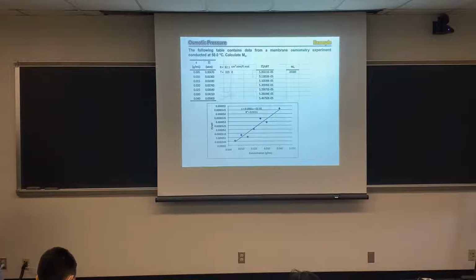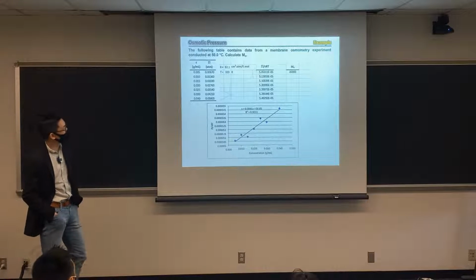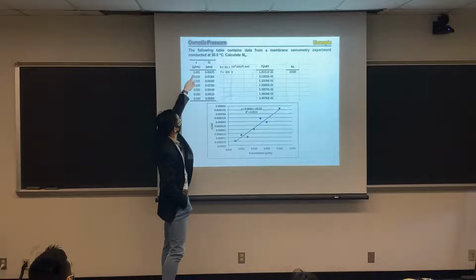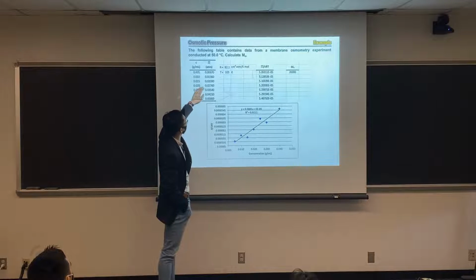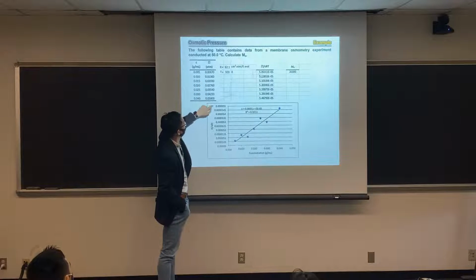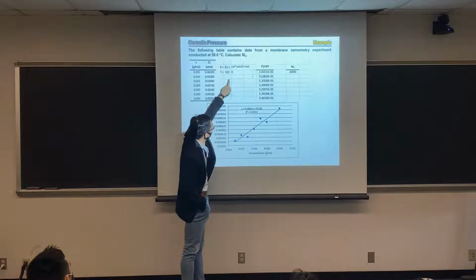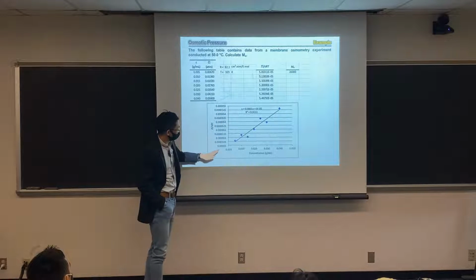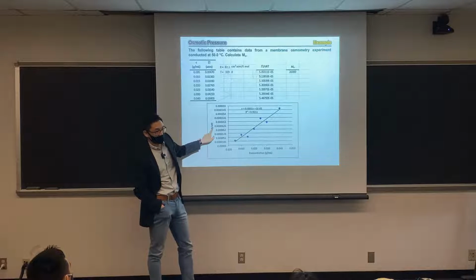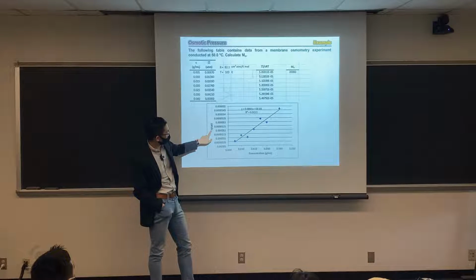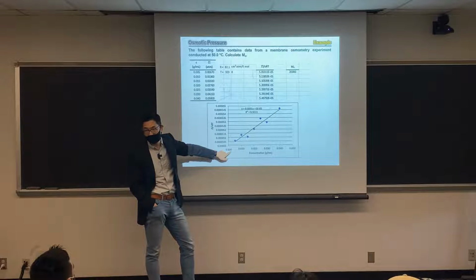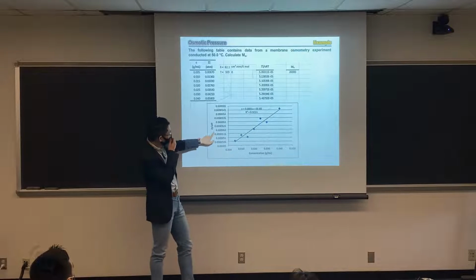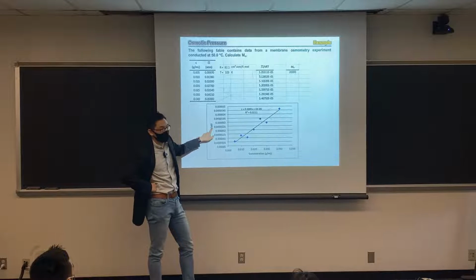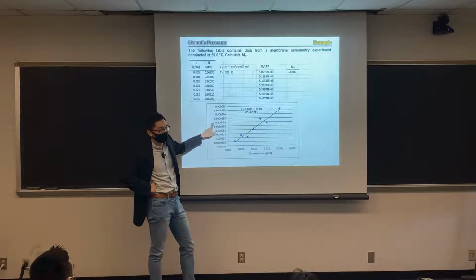This here is an example of how you can use real experimental data to compute the molecular weight. You can prepare the polymer at different concentrations and measure the osmotic pressure, and you know the gas constant and temperature. You can actually plot this particular curve. Pay attention that we're not plotting osmotic pressure directly against the concentration. We need to plot osmotic pressure divided by concentration and RT, okay?